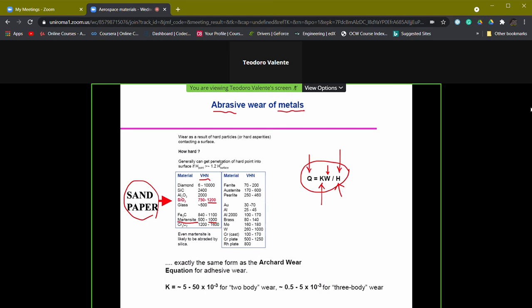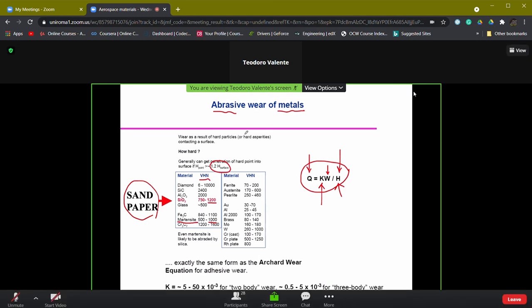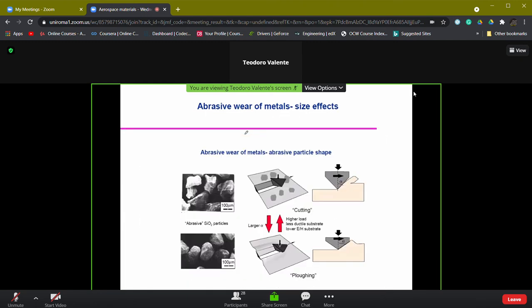Keep in mind that we do not need to exceed a 20% difference in hardness, otherwise we protect the weaker component, but highly consume the other component, which can become weaker in terms of final hardness.